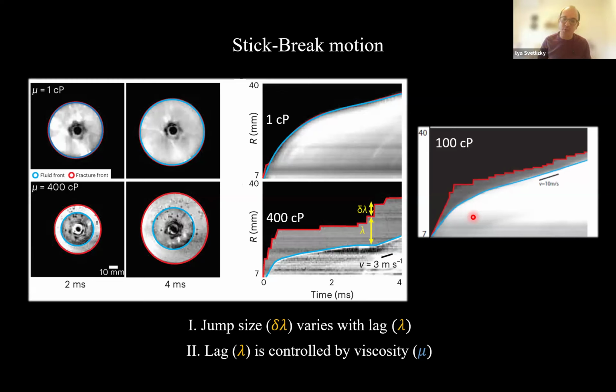And it's a delicate question. You can ask how much of the fluid is actually inside the crack, how much of the fluid is inside the tubes, how much the tubes were expanded. All these details we worked out, but they are not contributing much. So what we don't really understand is why different viscosities give you pretty much the same expansion rate. All of the experiments run at about 3 to 10 meters per second. And this is a result that I'm not sure how to explain. Does it make sense?